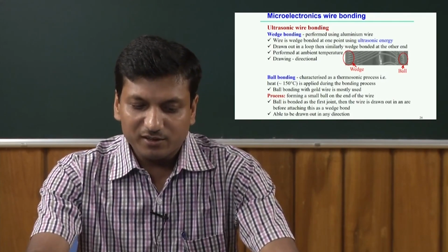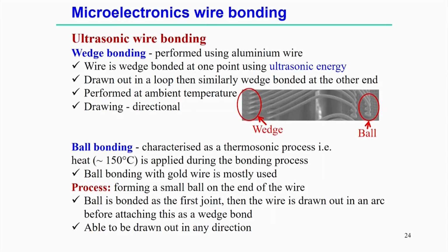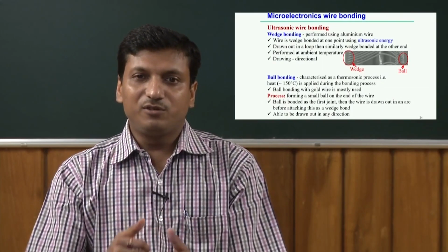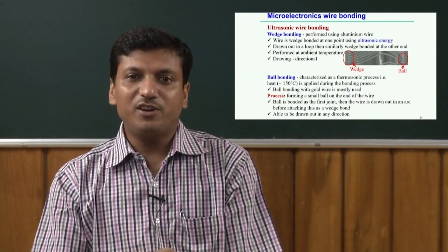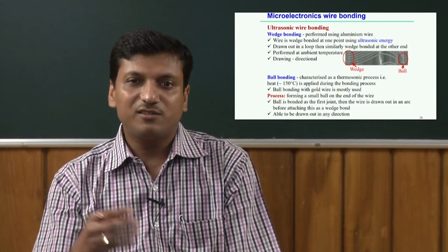Ball bonding, on the other hand, is characterized by the thermosonic process, because apart from the ultrasonic energy, some heat is required to get the ball bonded sample. In this case, ball bonding is mostly used with gold wire, and a small ball is formed at the end of the wire. Once the ball is bonded at the first joint, the wire is drawn out by forming an arc, before attaching it as a wedge bond to the other part of the sample. So ball bonding is joined in such a way that it can be drawn in any direction, which is a limitation in case of wedge bonding, because wedge bonding cannot draw the wire in any direction. So that is the difference.